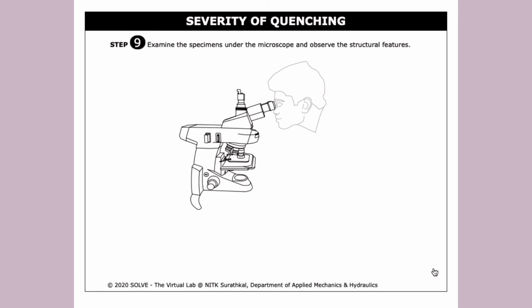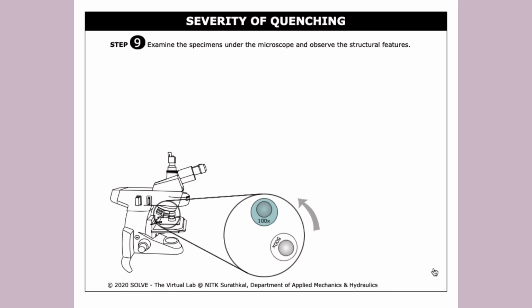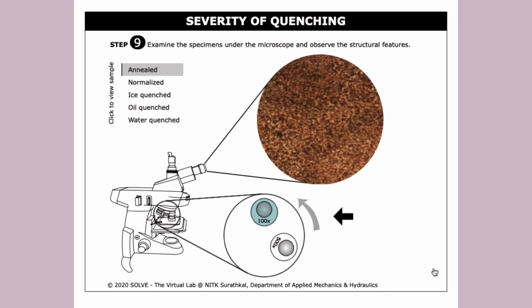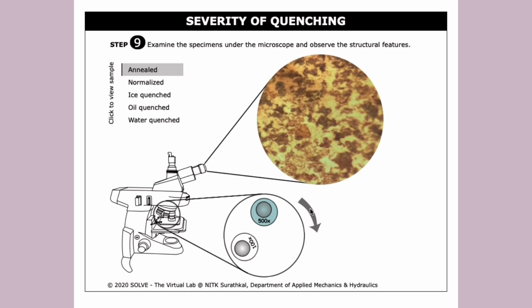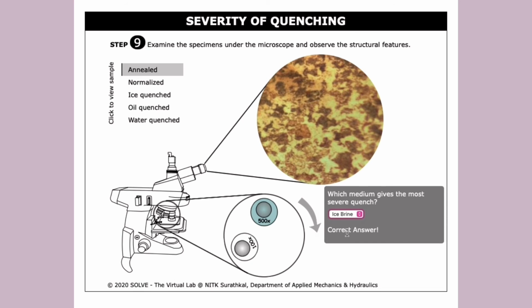The next step is you must examine the specimens under a microscope and observe the structural features. So by adjusting the microscope, we can have a clear picture of the structures of the features. As we complete this step, we know the ice brine gives the most severe quench.